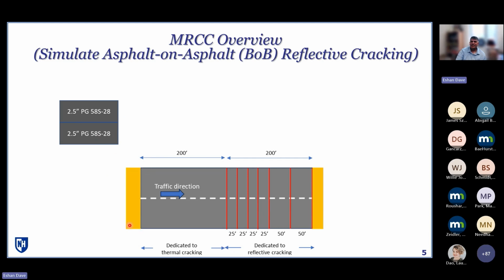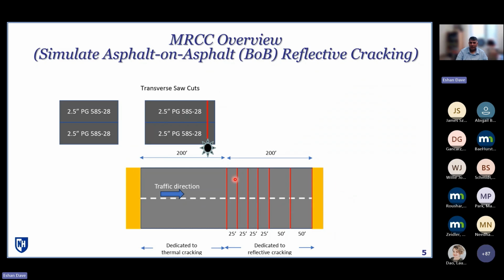Once that was done, and each cell is about 500 feet long, so there's 400 feet of actual monitored or instrumented area just to avoid the transition areas at either end. Within that 400 feet, it was further divided into 2 portions. So you have a 200 feet portion, which is like your classical flexible pavement. And then in the second 200 feet portion, after initial construction, transverse saw cuts were made within that section, and that's what is represented with these red lines. So you can see the type of saw cut: initially a 25 feet spacing between these transverse saw cuts, and then a 50 feet spacing.